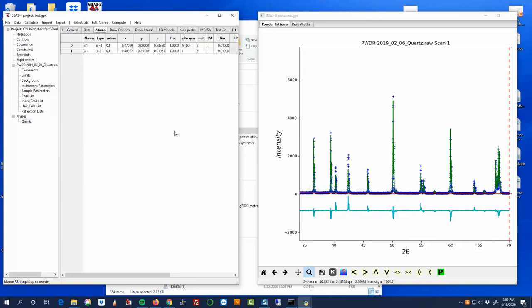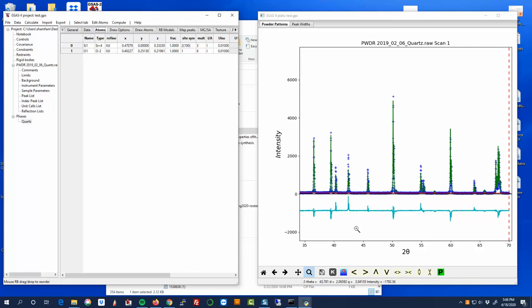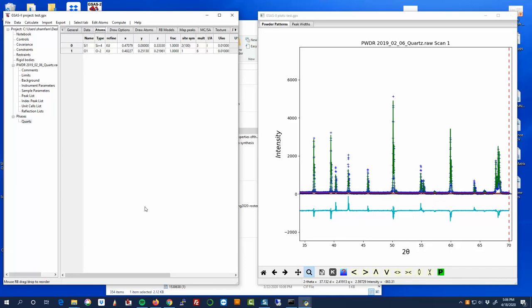My guess is this is just a dataset that we pulled off a lab system. And, you know, because the intensities are off, there's a chance that we have some sort of preferred orientation going on in this particular sample. Depending on how you prepare the sample, you can actually unintentionally introduce some orientation and alignment effects. And that would cause certain planes to look higher than others. These are things that you can try and work out in the refinement process. But we're not going to go through that step today.